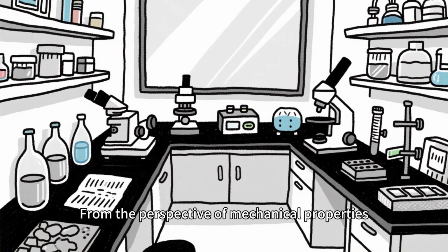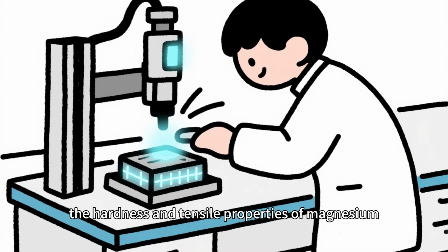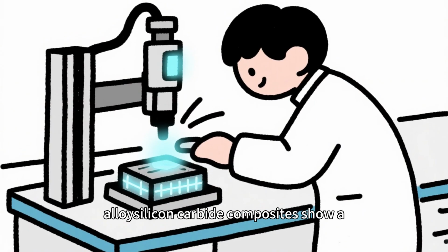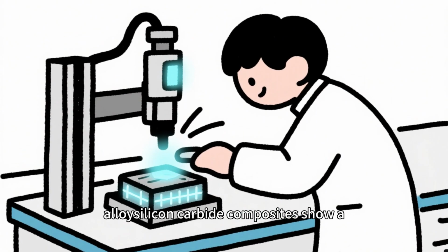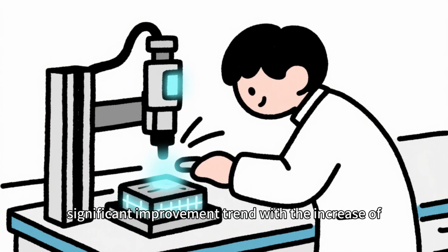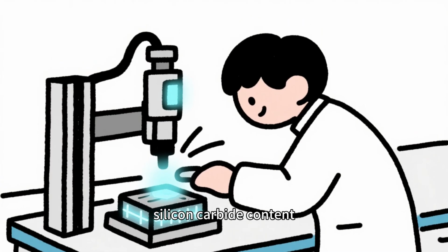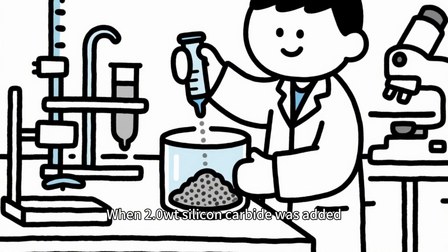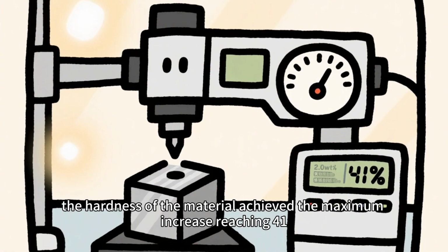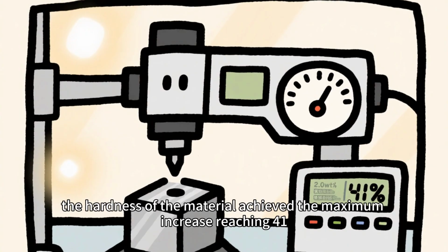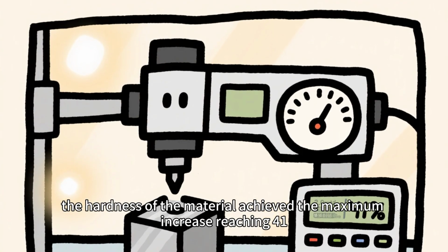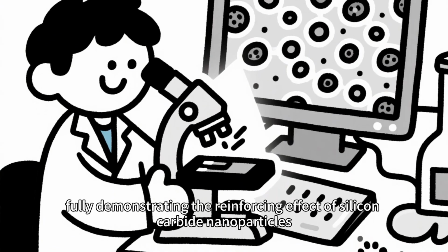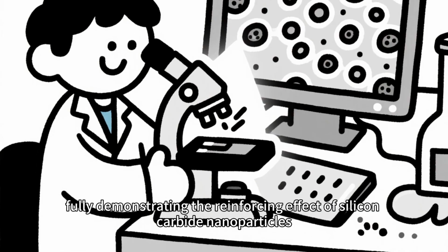From the perspective of mechanical properties, the hardness and tensile properties of magnesium alloy-silicon carbide composites show a significant improvement trend with the increase of silicon carbide content. When 2.0 wt% silicon carbide was added, the hardness of the material achieved the maximum increase, reaching 41%, fully demonstrating the reinforcing effect of silicon carbide nanoparticles.